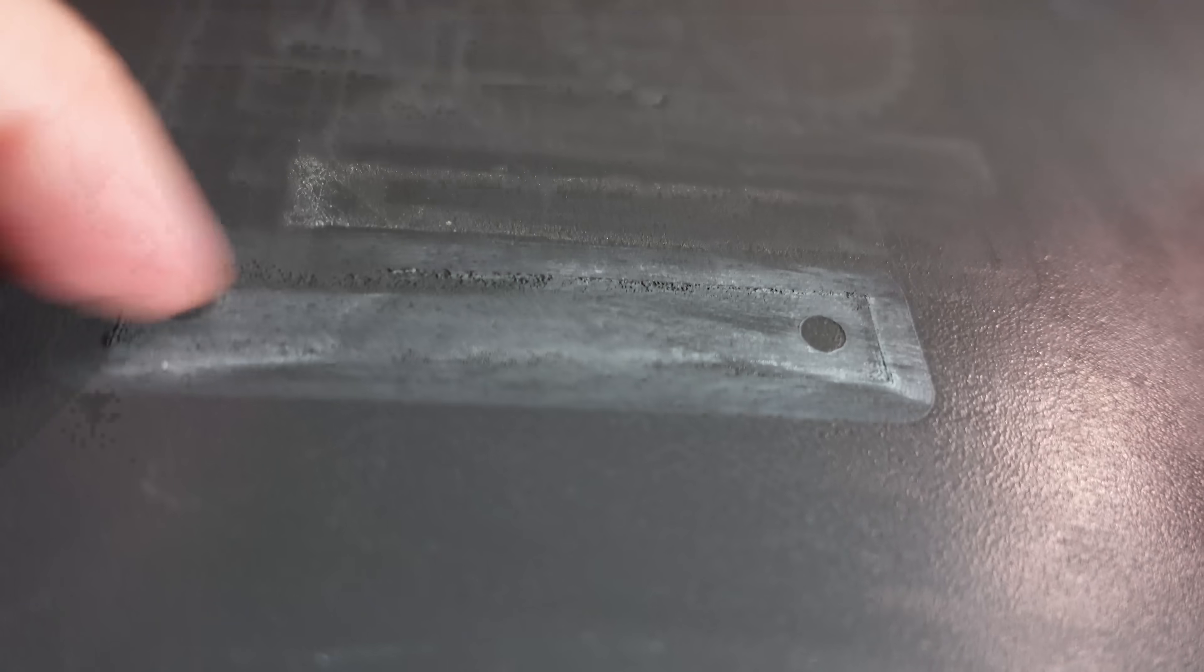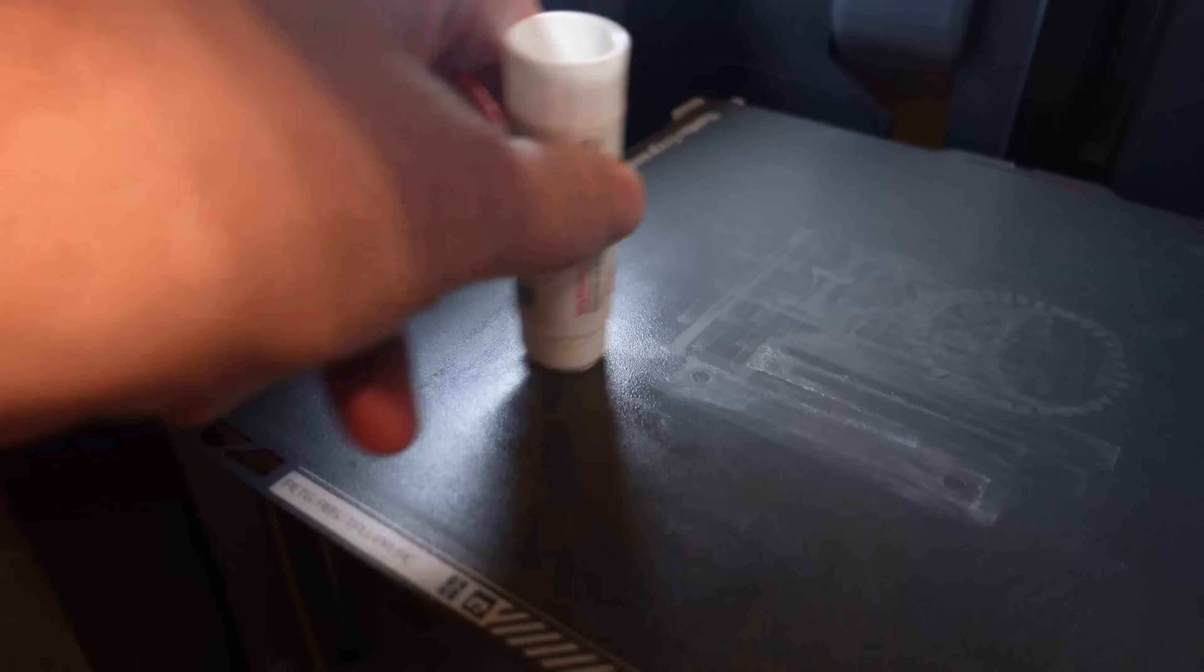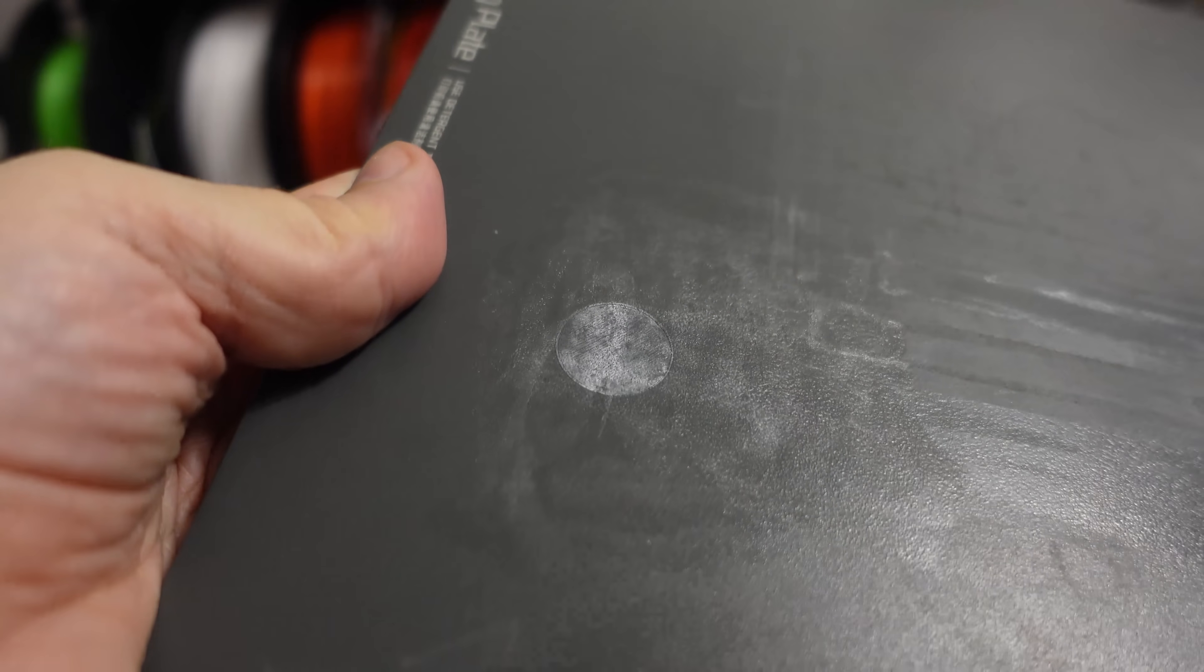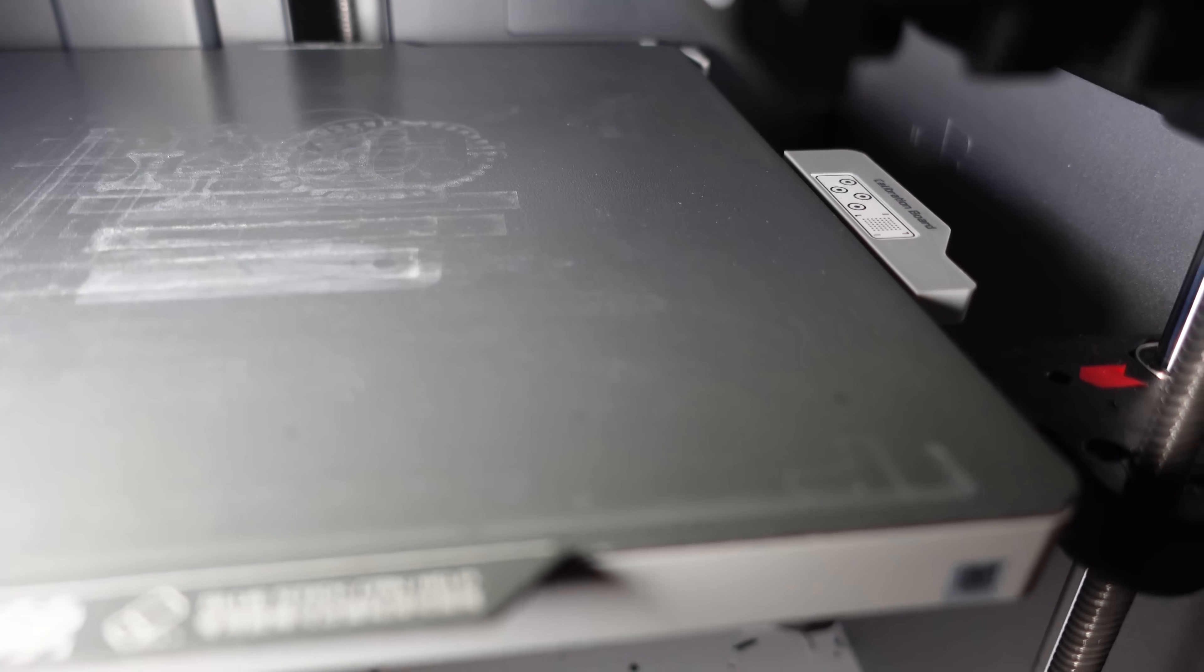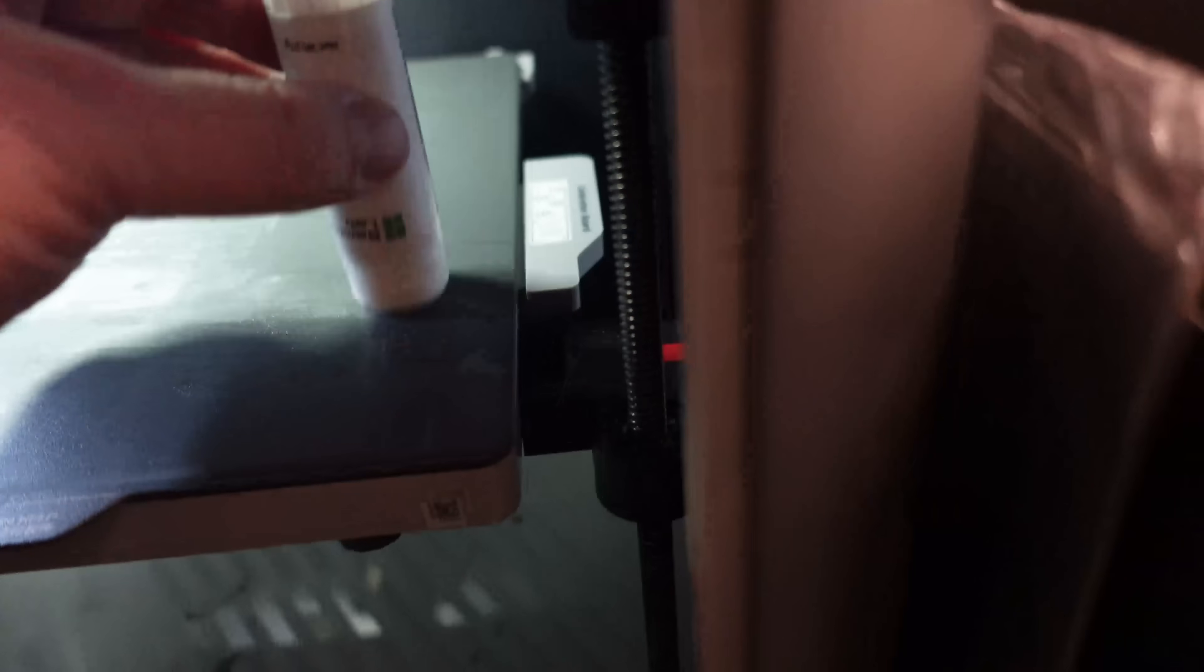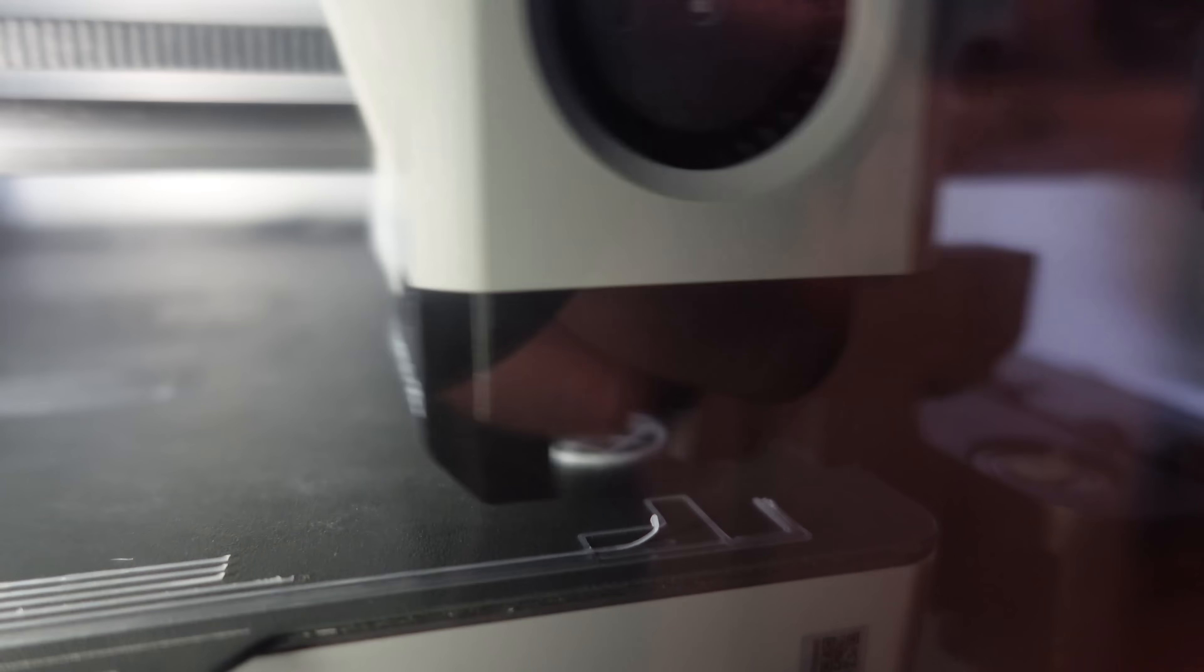Oh, this is not good. I want to investigate this problem a little bit deeper. Remember I am printing a cylinder in this corner. No mark here, but now let's add some glue. Reprinting the same object, but this time with the glue. And the mark is there again. One more time in this corner. And here I can see I don't have the glue, unfortunately without glue it doesn't stick. But the point is there is no mark on it. Now let's add some glue. I am ruining my engineering plate, which is discontinued. But I really want to investigate this. Not sure if you can see it, but it's there. But by time I noticed that it became smaller, for example here when I printed that gear.